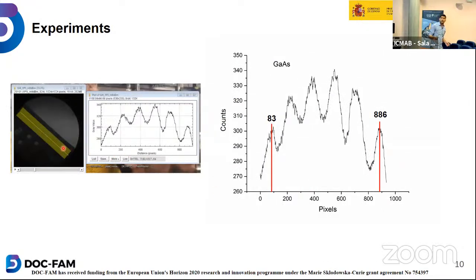This is the gallium arsenide. This is the piezoelectric material on which we deposited here. This is copper manganese arsenide, the antiferromagnet, and this is another piezoelectric material. Here we draw a line width profile, and we see the waves. This is not the actual scale, which I show here in the big counts. It's just a rough thing.